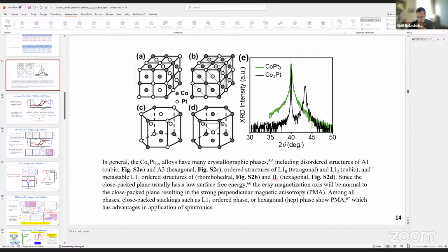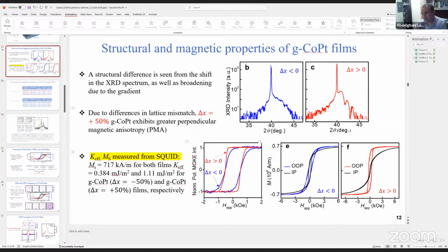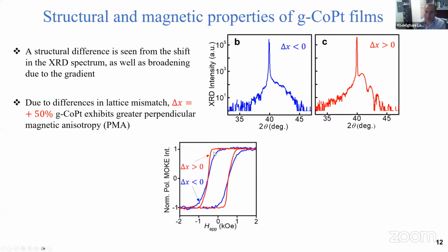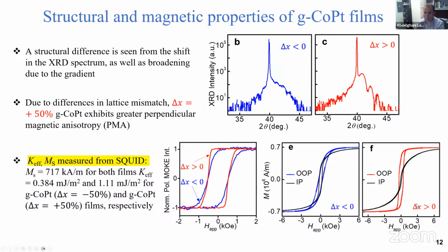Okay, I see. But is there some uniaxial anisotropy in any case? That's a very good question. In principle, for the positive gradient, they have almost PMA, perpendicular magnetic anisotropy. For the negative one, it seems they have some in-plane magnetic anisotropy, but I need to check whether it's initial. So you have an easy axis? Yeah, for the positive, you see it perfectly.